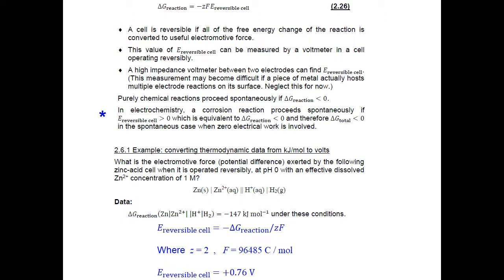So remember, pure chemical reactions went forward if the Gibbs energy change of reaction was negative. In electrochemistry, we have the same thing in principle. The corrosion process proceeds spontaneously if the total Gibbs energy change of the system is negative, but what we write this as is: the corrosion proceeds spontaneously if the reversible cell potential is positive, in other words, if it could supply some work.